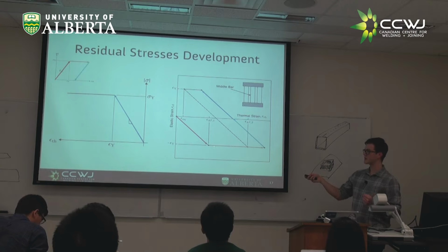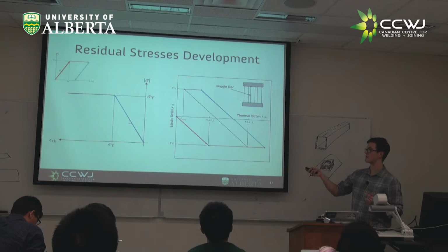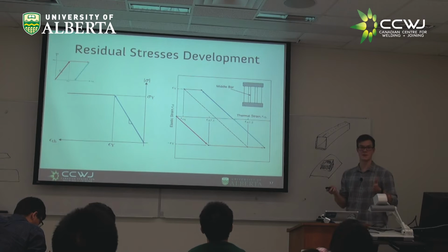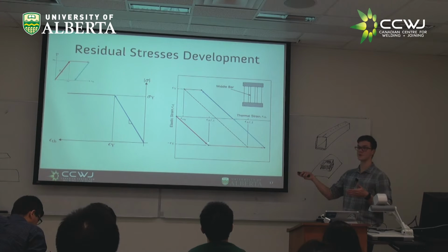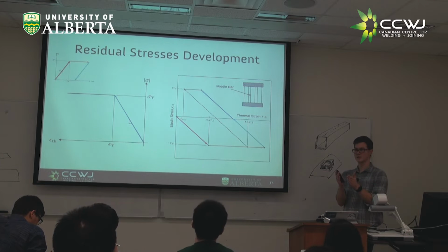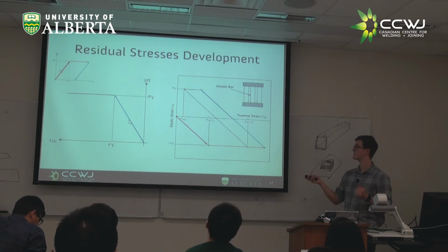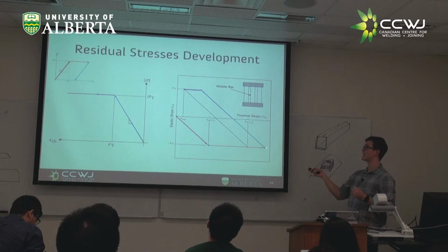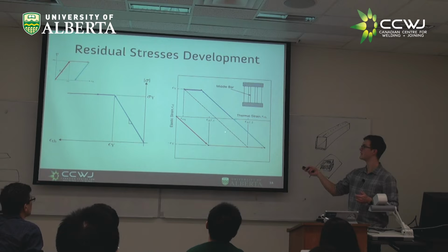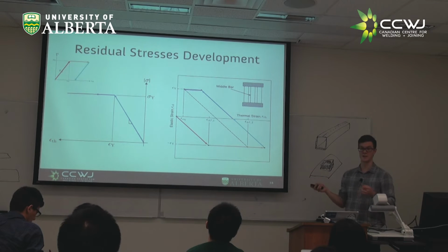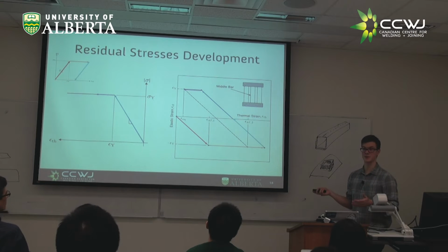If we heat even a little bit beyond this point, when we return back along our constant elastic recovery line, we're going to have some amount of residual stress. So this temperature is going to be a really critical temperature for understanding stress, because this is going to be the boundary from where we have no stress to where we have tensile stress. And you can imagine that if we have really high temperatures, we have some plastic strain upon cooling. But really what we're interested in is this: any heating beyond this point, we're going to have some amount of plastic strain, some amount of residual stress.